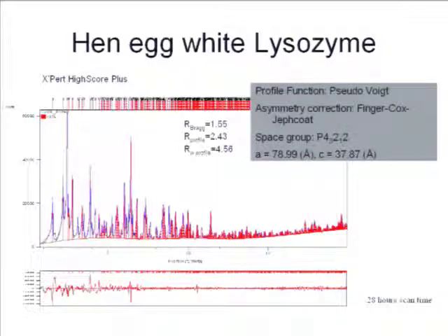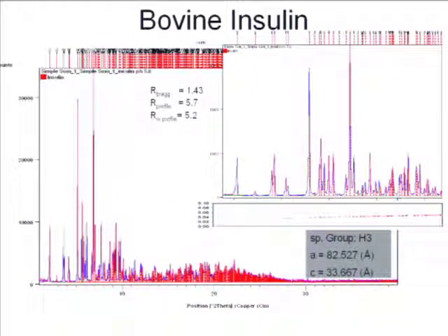The sample resists because the dose rate in the lab is much, much less than in the synchrotron. And this is a pattern for the hexagonal insulin. Again, good enough for indexing and a little bit further in our analysis, good enough for doing a first screen of the various samples.